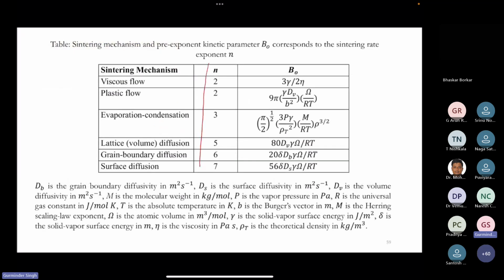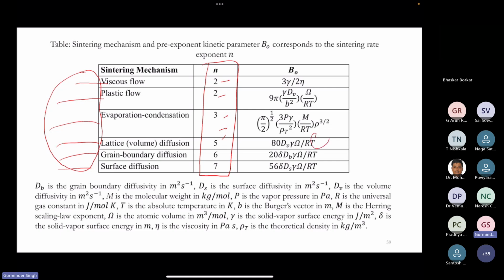As per the literature, if you have some n value, you can easily find out what type of sintering mechanism was there, because it is very important to know about the sintering mechanism to get better diffusion, so that you can control the temperature, the soaking time, and the powder particle size. So you will be able to know which is the most efficient sintering mechanism for any particular material.